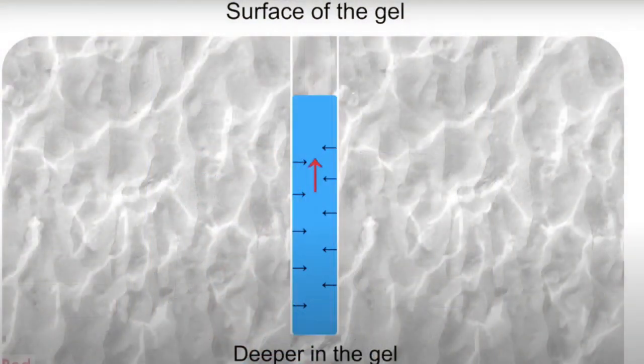And while aerogel does sound very promising, like many new technologies, it does come with a huge cost. However, recent innovations have taken enormous steps forward to decrease costs and increase the scale of aerogel. Where these costs come from is the process of replacing the liquid with gas to fill the aerogel. Intuitively, one might say that you should evaporate the liquid to liberate the pores and have gas. But what this actually does is create what's called capillary action, which causes the liquid in the bottom or in the center of the gel to move up and cause the structure to collapse. And so there needs to be another way to replace the liquid with the gas.